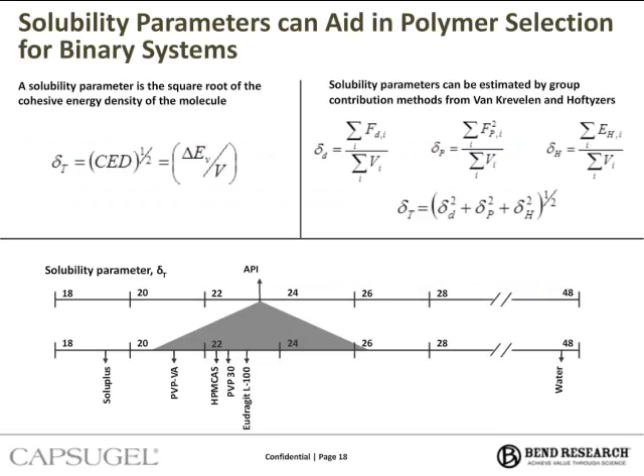So we first start attacking this question by using solubility parameters. And solubility parameters can be used to predict the miscibility of two substances by determining their individual cohesive energy density. Now, things with similar cohesive energy densities are likely to be miscible. Now, solubility parameters for polar molecules can be calculated according to Hansen, and that's in the upper right. One of the preferred methods we use to calculate this is a group contribution method, and we will typically use the Van Krevelen and Hoftyzer group contribution methods. And we will average those two.